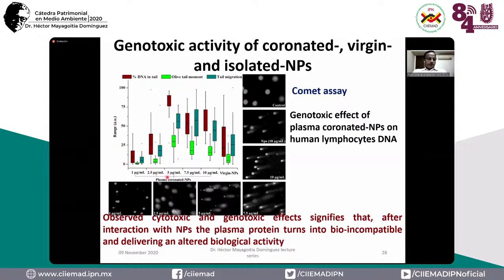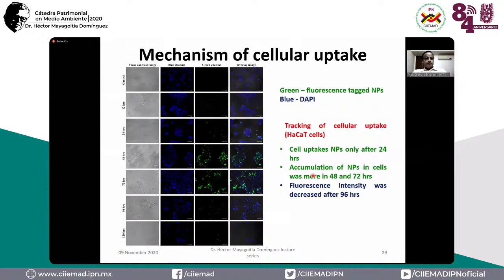So this is their range, and this is the plasma coronated nanoparticles and different concentrations of virgin and coronated nanoplastics. We also isolated nanoplastics from different consumer products, and we could see that nanoplastics were able to induce a genotoxic effect in human lymphocytes. Then we did a study with cells, the human HaCaT cell line, which is a skin cell line.